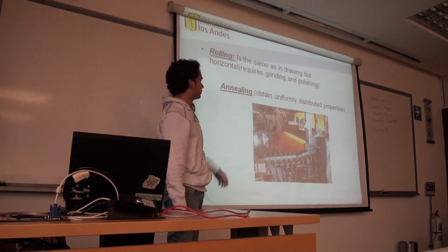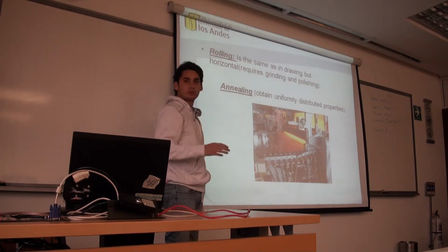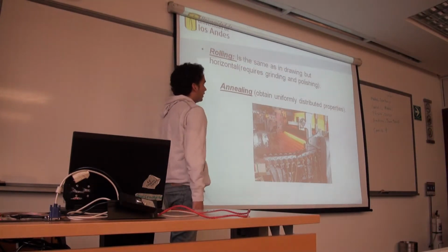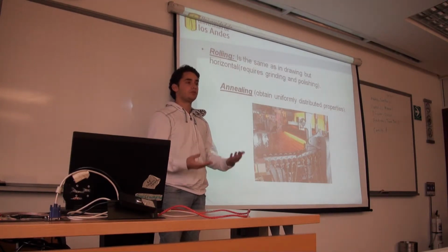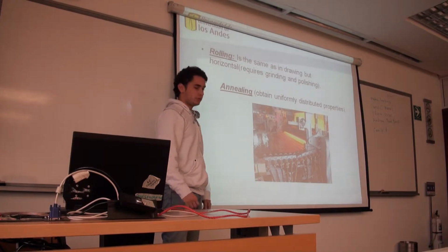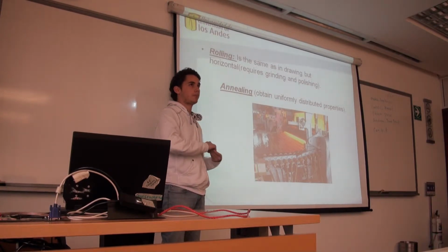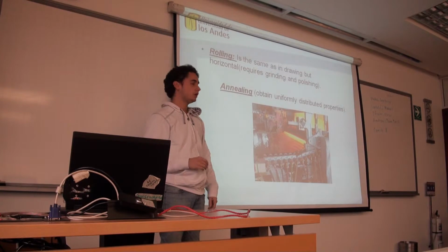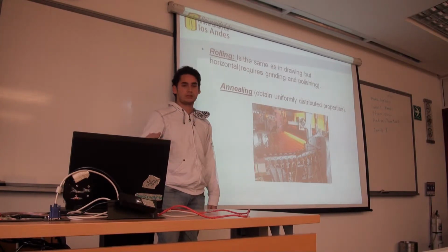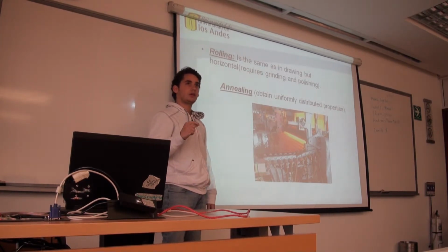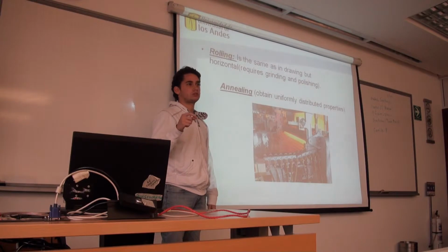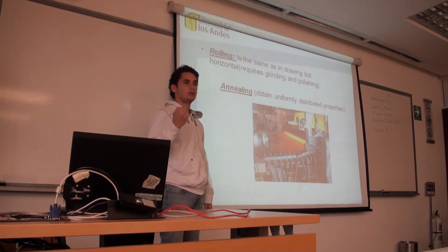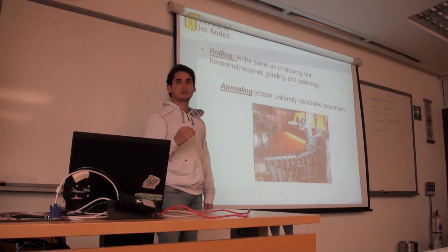An extra stage that is common for the three techniques is annealing. What you do in annealing is improve the properties of the glass, because after you do the heating of the glass and then the cooling, you create a surface that is not homogeneous, and you create little spaces in the glass, and those become stress concentrators, and then you will have a lower resistance of the glass.